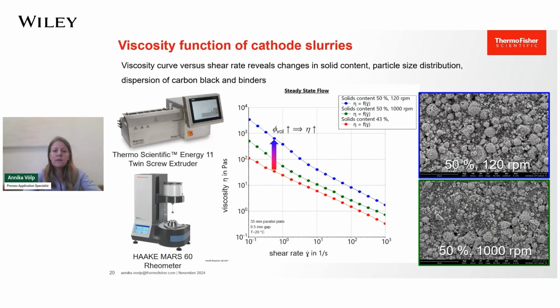With increasing solid content of 7%, the viscosity increases by more than a decade at a shear rate of 1 reciprocal second. However, the viscosity of the slurry with 50% solid content can be reduced significantly by applying higher shear forces in the mixing process with the higher extruder screw speed.